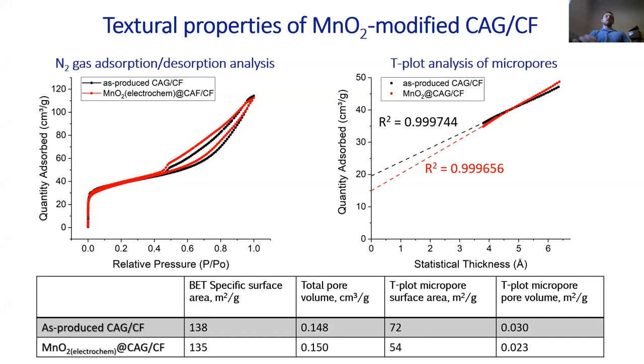The gas adsorption analysis, which shows us the surface area of the material, indicates that the two isotherms of as-produced carbon aerogel and the manganese oxide decorated material, electrochemically deposited, are quite similar in terms of shape as well as in resulting values of total surface area and pore volume, which shows us that deposition of manganese oxide does not cause any drop of surface area due to, for example, blockage of carbon aerogel pores. On the other hand, the t-plot analysis indicates a small drop of the micropore surface area and volume, which actually can be beneficial considering possible diffusion limitations caused by slow diffusion of electrolyte ions inside of the carbon aerogel pores.